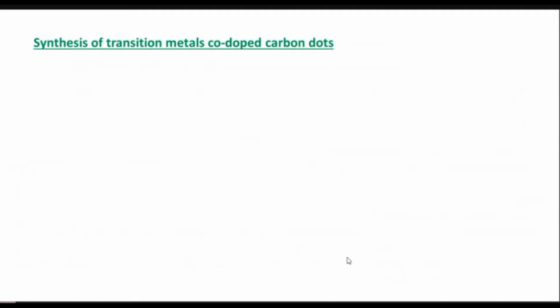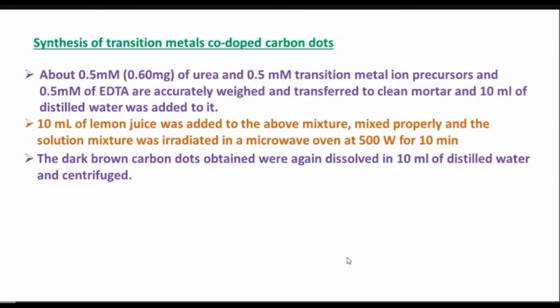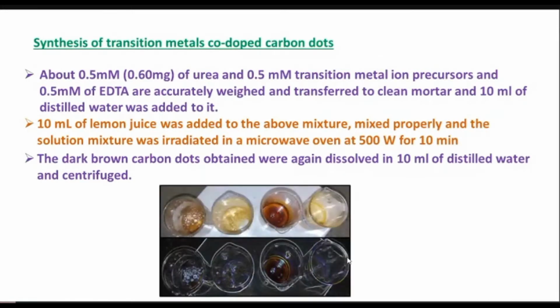The second synthesis strategy is that of the transition metal co-doped carbon dots. It takes place as the previous one itself. The only difference is that we have used the first row transition metals as the precursors and follow the same procedure. This is what we obtain after the carbonization has taken place.